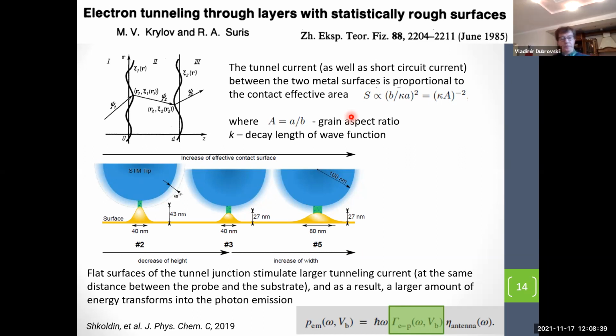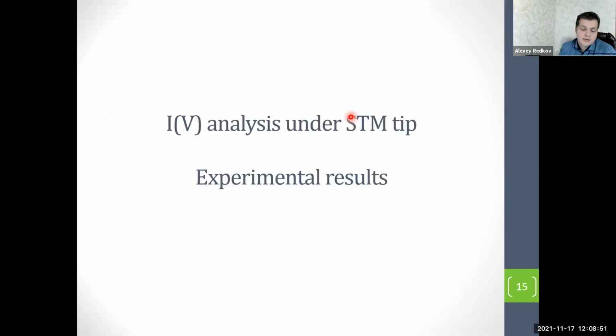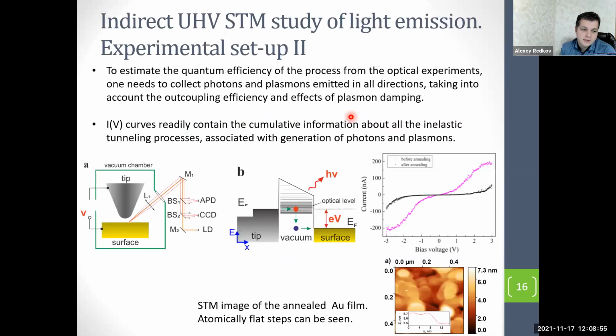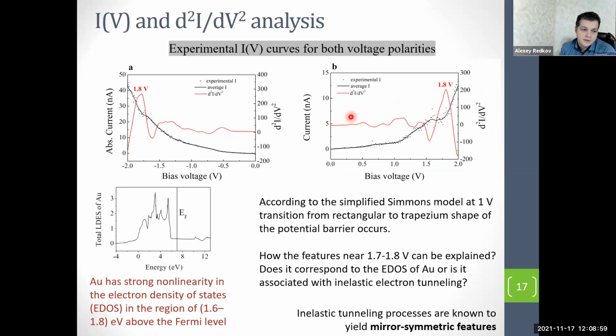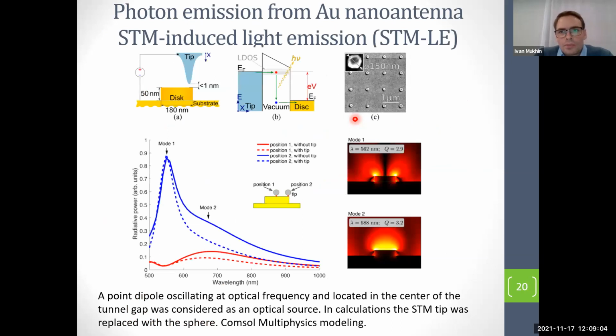Thank you. Alexei, please. Ivan, thank you for your talk. I have a very short question. You performed experiments mainly with gold nanoantennas. Can we expect all the same effects with silver nanoantennas, but at shorter wavelengths? Or is there something specific behind using gold? It was shown that material properties of contacts can modify the emission spectra in STM. So silver nanoantennas should also work. And I suppose that the main position of the plasmon mode will be governed by the size of the nanoantenna, but also by material properties. So in that case, you will shift the position of the peak. Okay, thank you.